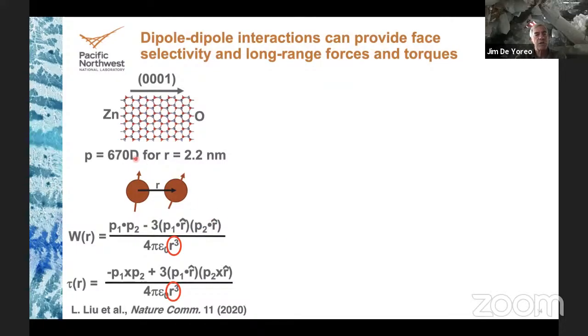It's not huge. It's about 670 debye for a 2.2 nanometer particle, which is the average size of the particles in our TEM experiments. But we know that particles that have dipole moments are going to align themselves, right? And the attractive interaction is going to be like the van der Waals term. It goes like 1 over r cubed. And the torque is also going to go like 1 over r cubed.